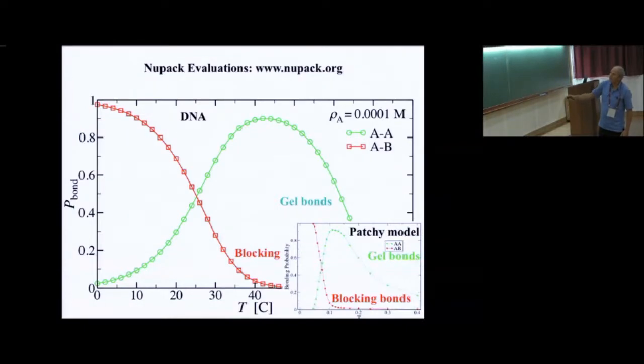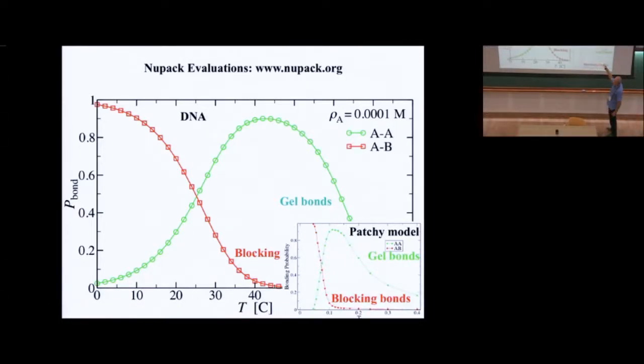Above 40, we will have a gel, according to the theory, and below 40, you will have the blocking that starts to form, and then the gel that starts to melt. And if you compare with the results of the simulation that we had, it's really very similar. Actually, it's even much better if you think about it.